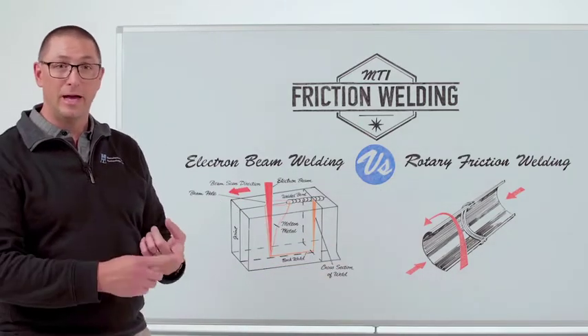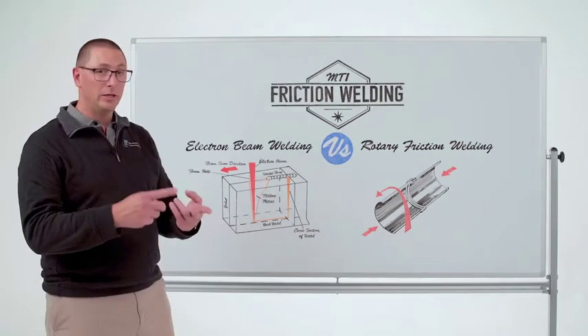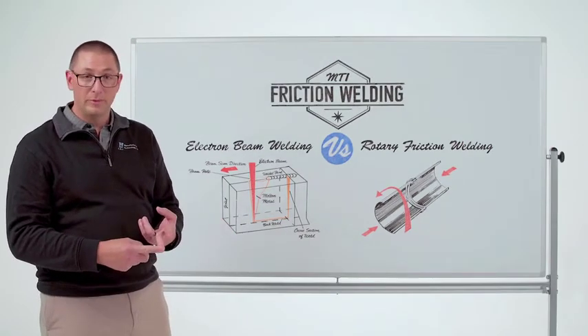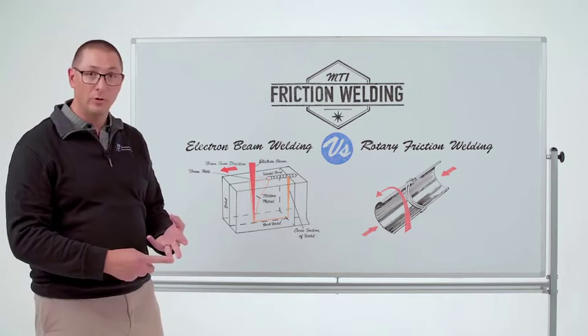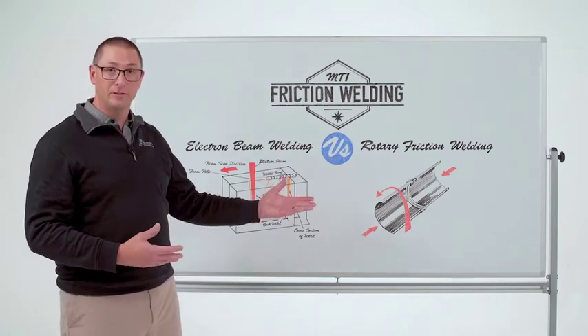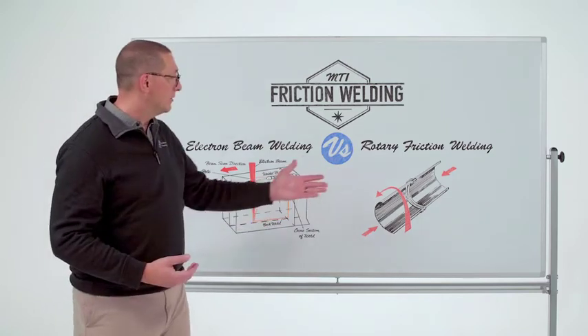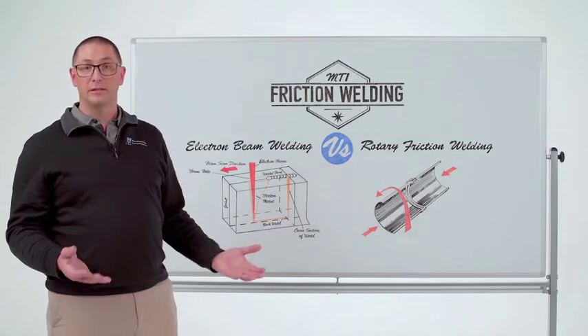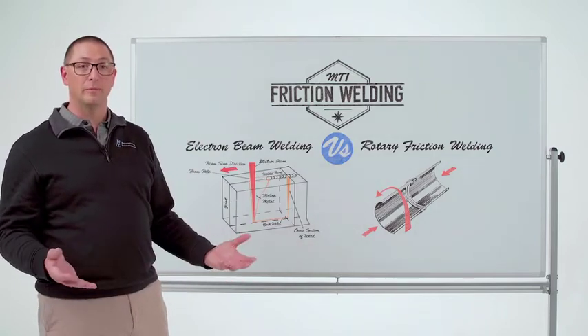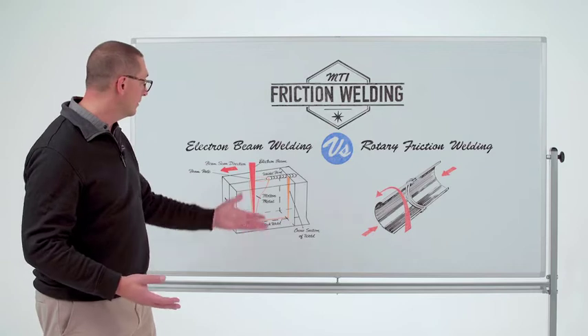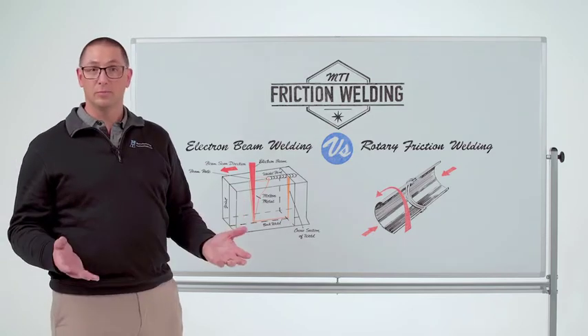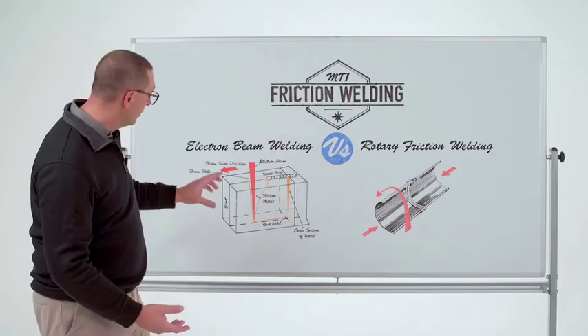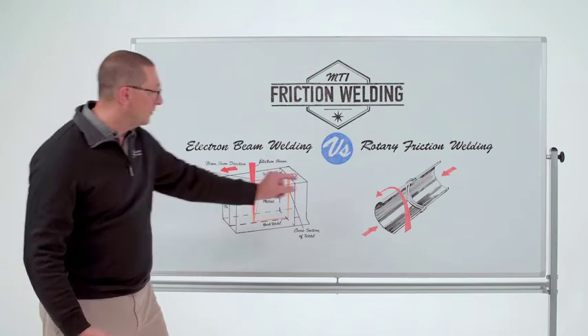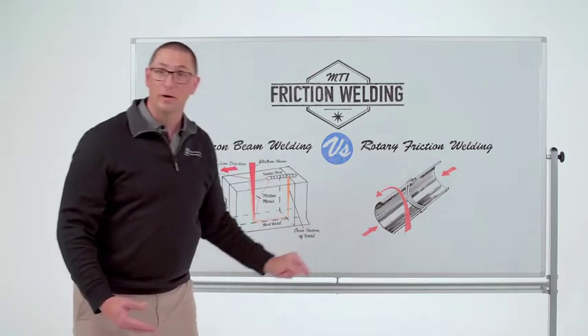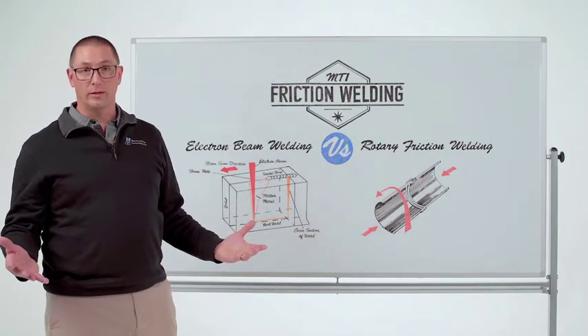So it's not done in an atmosphere. There's very little pre-machining that you need to do, but there will be post-machining. The biggest difference between the two processes is that a friction weld is a solid-state joining process. So you're getting parent material strength in most cases compared to a melted product, and therefore, with an EB weld, you may have to increase the thickness of the part in order to get the joint strength that you want.